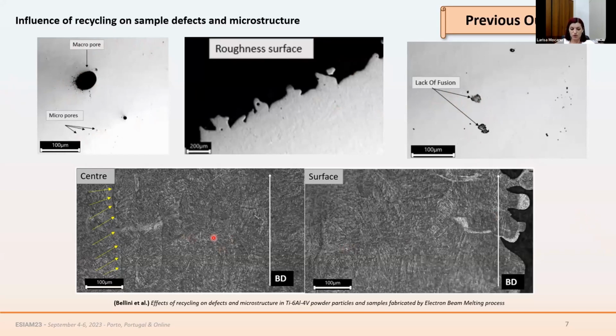Regarding the microstructure, no particular differences were observed between the three kinds of components. They exhibit mostly a basket weave microstructure. And something interesting was the prior beta grains, which tend to follow the building direction, but this was observed only in the center of the component, and close to the surface this was not observed. This was also observed in all three components. So also here the influence of the recycling is not visible.